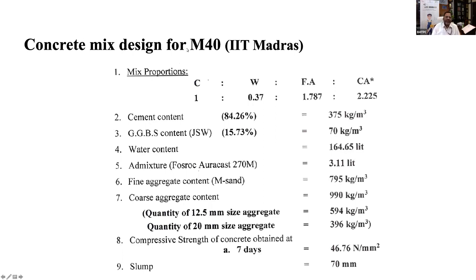And, I was telling you, M40 stands for the compressive strength of the concrete cube, 40 newton per millimeter square, and by using this concrete mix design, we are achieving a concrete strength at 7 days of 46, which is far above your 40. So the entire material optimization, use of waste material, use of admixture for early strength, and getting better compressive strength, make your concrete and the design sustainable and green.